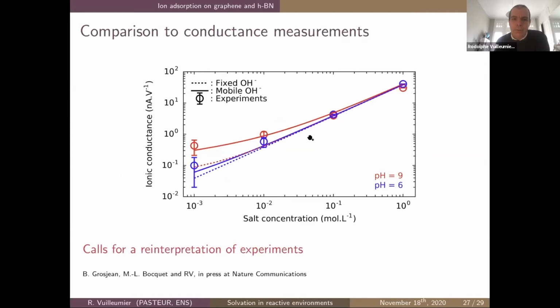So the circles are experiments, so measurements of conductance, not of surface charge anymore. And the dotted lines are the result if we fix the OH minus, if we neglect the diffusion on the surface, and the full lines are the results of our model by putting the free energies that we compute, and by putting an estimation of the diffusion coefficient of OH minus on the surface. And you see that we fit very well with experiments, much better than if we neglect the surface conductance. So this calls for a reinterpretation of experiments, because it means that the surface charges, which were also extracted from ionic conductance from this analytical model, should be corrected to get more precise surface charges.